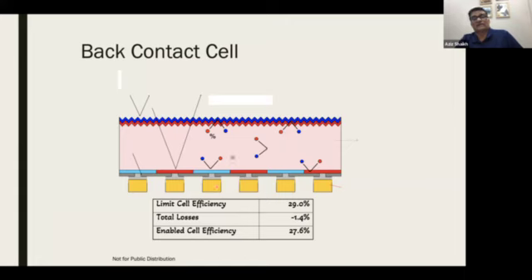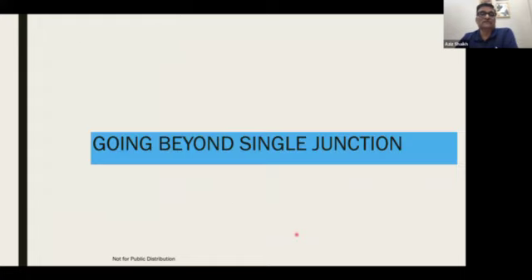And what it is showing you is the recombination on the front side, recombination within the silicon, recombination at the backside. So efficiency limit is 29%. The total losses are 1.4. So SunPower is able to achieve very high efficiency, 27.6. And so does HJT. Okay. So now what do we do?